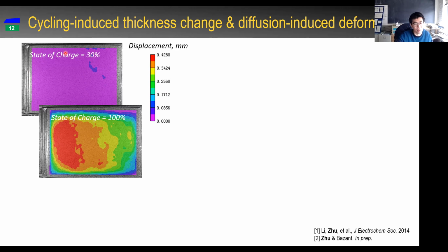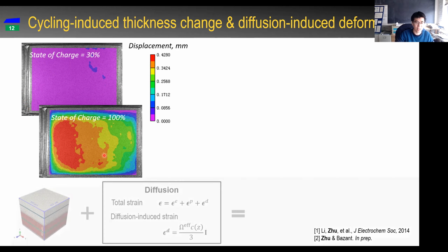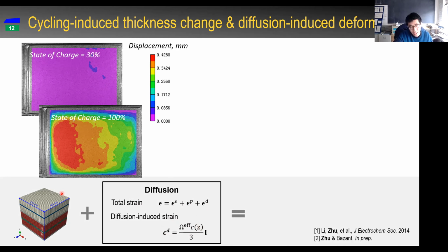So we use the DIC, digital image correlation method, to measure the thickness change of the battery, and we see that at 30% state of charge, there is almost no deformation yet. However, at 100% charge, we see a severe displacement field. So how to model this kind of thickness change of the battery cell? This is a task for us, and we now implement some diffusion equations into the solid mechanics model. And again, this is part of the physics, part of the equations. The decomposition of the total strain is elastic, plastic, and the diffusion-induced strain. And the diffusion-induced strain is correlated with the concentration of the lithium ion in different layers. So in this way, we can give predictions.